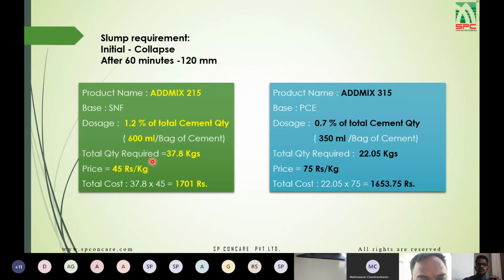Now the total quantity of 215 required is 37.8 kgs at 45 rupees per kg, which gives a total cost of 1701 rupees. On the other hand, for the 315 the total cost is 1653.75 rupees. Here you can see the final cost of the PC based admixture is lesser than the SNF based admixture. Why? Due to the lower dosage of the admixture. At a lower dosage it provides better performance than the SNF based one. So even if it has a higher price than the SNF base, finally due to the lower dosage it comes out equal to or lesser than the SNF base.